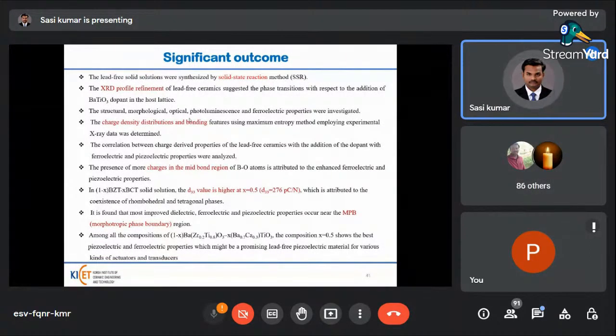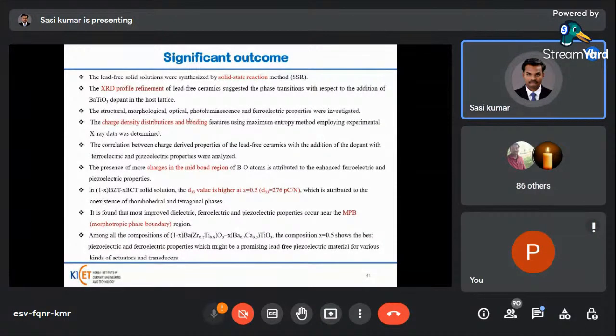Among all the compositions of lead-free piezoelectric ceramics, barium zirconium titanate, barium calcium titanate, the x equal to 0.5 composition has better piezoelectric and ferroelectric properties. It might be a promising lead-free piezoelectric material for various kinds of actuators and transducer materials. So far, we have developed many lead-free piezoelectric materials, which are mainly used in actuators and transducers, and also some sensor applications.